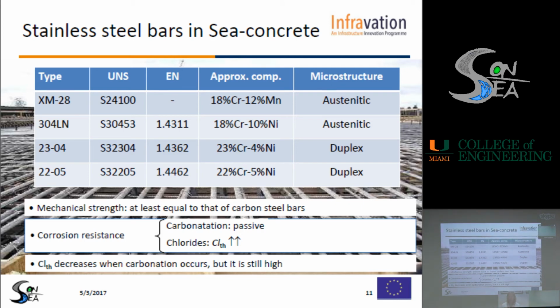corrosion resistance. They are passive in carbonated concrete, and the amount of chloride which promotes the initiation of corrosion is much higher than that of carbon steel bar. The carbonation of concrete may affect the critical chloride threshold, which is still high, however.